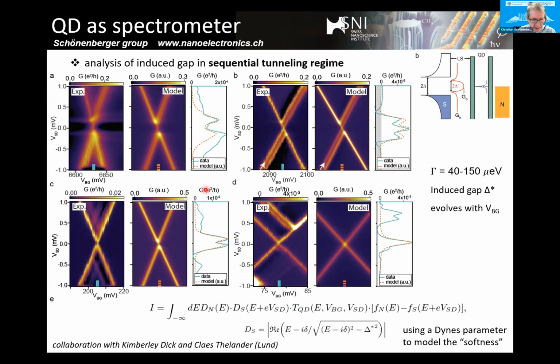Now, if you go further in gate voltage, now this goes to 6 volts upwards, you see the gap still doesn't change much in size. It just starts to blur here, but this is because the lifetime of the levels of the system gets very short, and the levels broaden quite a bit, and that's why it looks so fuzzy. So, okay, anyway, we can explain this quite well. We see an induced gap close to the aluminum gap, but it's always soft.